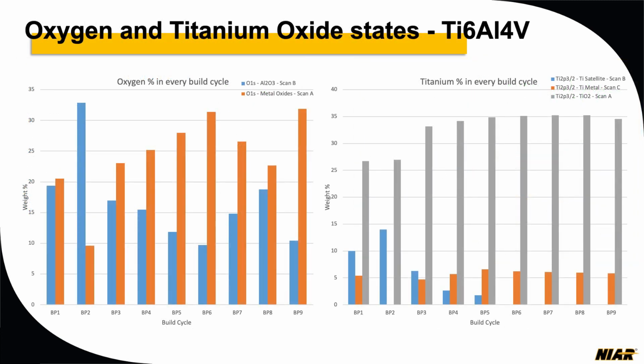This was a comparison on your bottom scale. You will see build cycle 1 to build cycle 9, so there were 9 build cycles. In the 3D printing part, they accumulated the powder close to the laser, trapped it, and provided that sample to me at a later stage. We analyzed, after 3D printing, the powder next to the laser, and how the oxidation affects it. They had done 9 build cycles, and they are shown here.